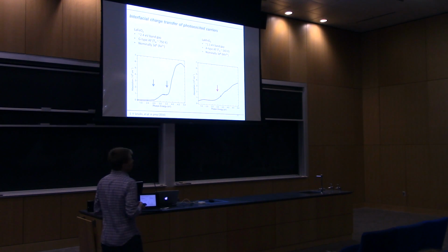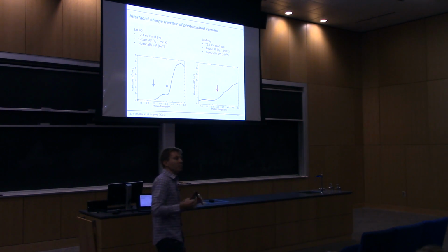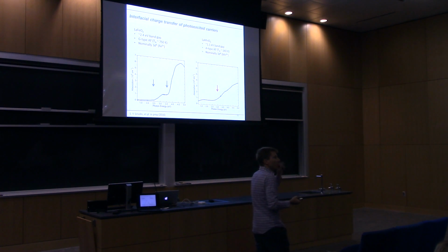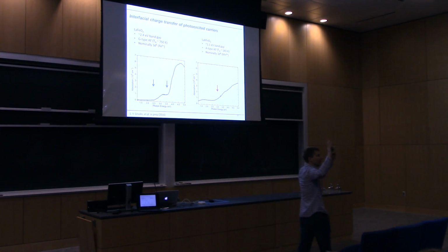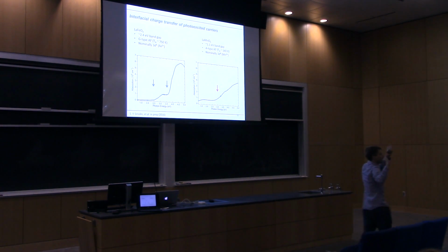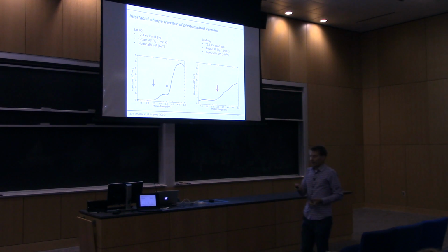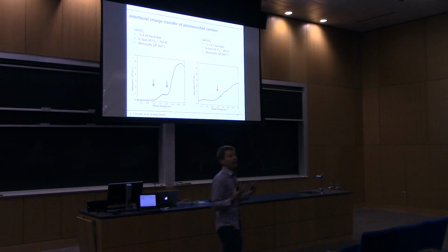All right, so we're just dipping our toes into this. We want to start with two relatively simple systems that have been characterized. We're going to take lanthanum ferrite and lanthanum manganite. Lanthanum ferrite is a semiconductor with a gap of about 2.4 eV. It's a G-type antiferromagnet with a very high Néel temperature. It has a nominal d5 iron 3+ configuration.